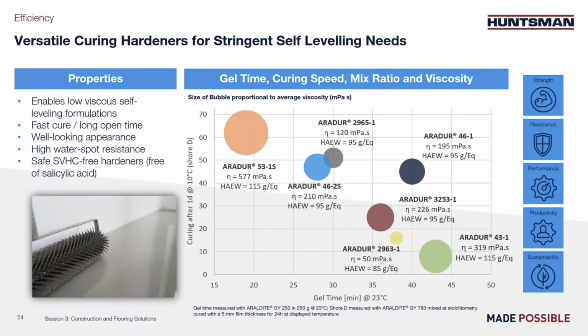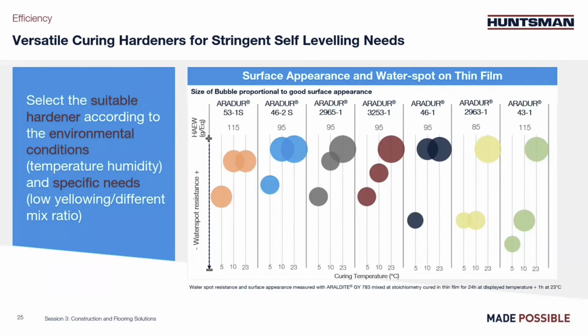The H plus equivalent weight mentioned relates to the mix ratio. Hence, if the H plus equivalent weight is 95 grams per mole, you need 50 parts of hardener for 100 parts of standard resin by weight. We can clearly see that curing development is linked with the gel time. So depending on the needs, the right compromise must be found. And another parameter in this range of products is water spot resistance and appearance. And we have tested those parameters on the next slide.